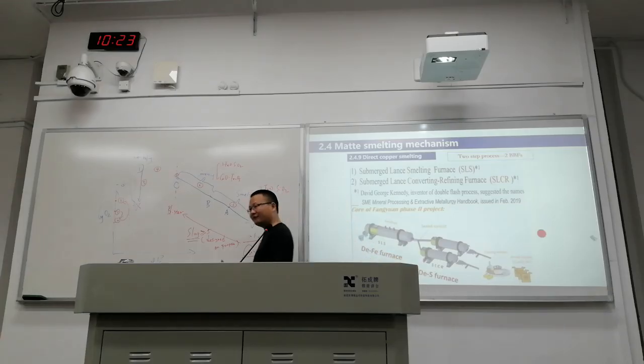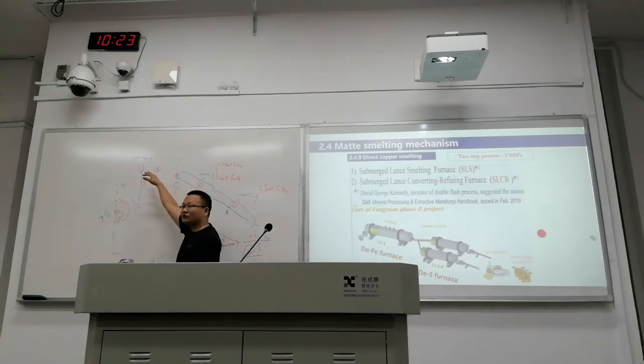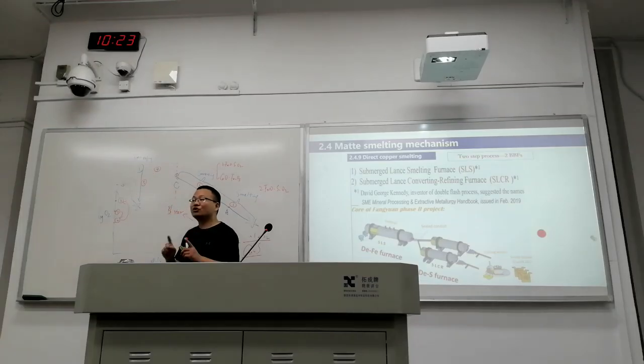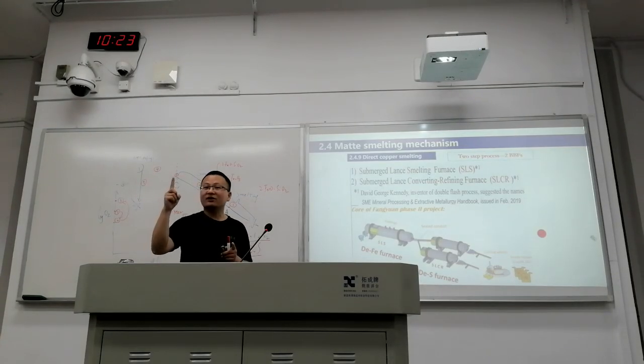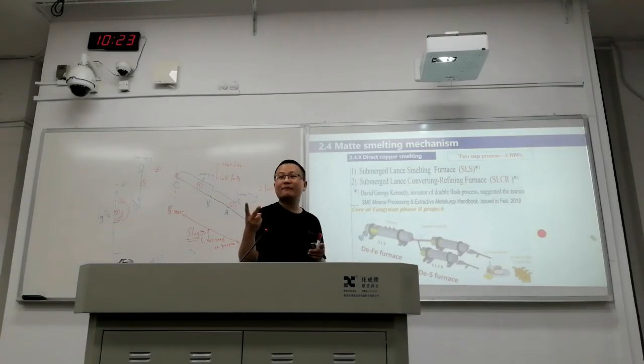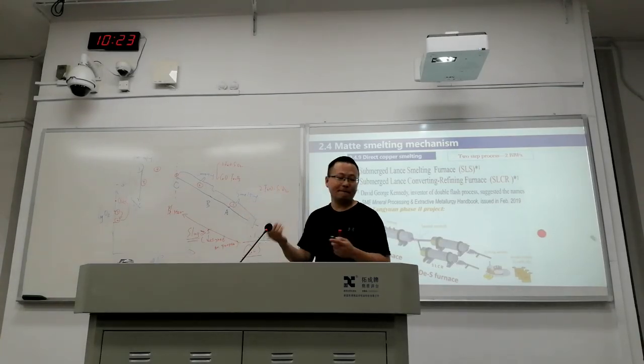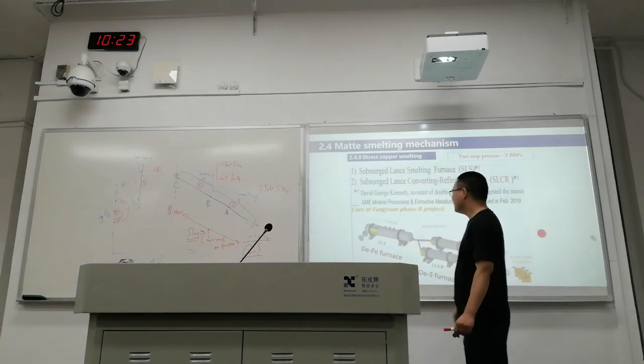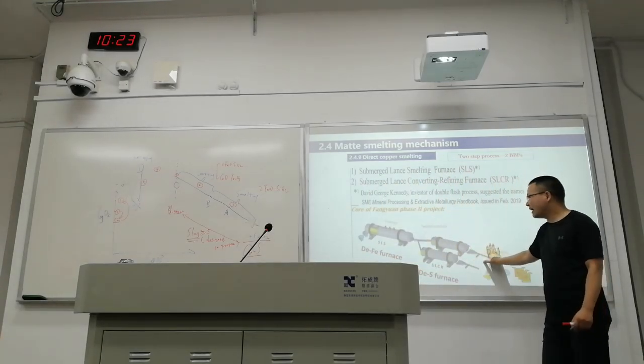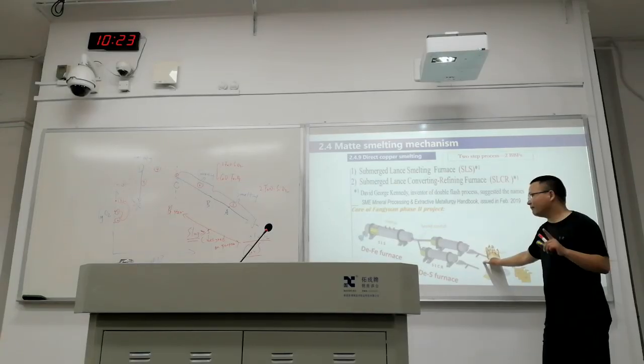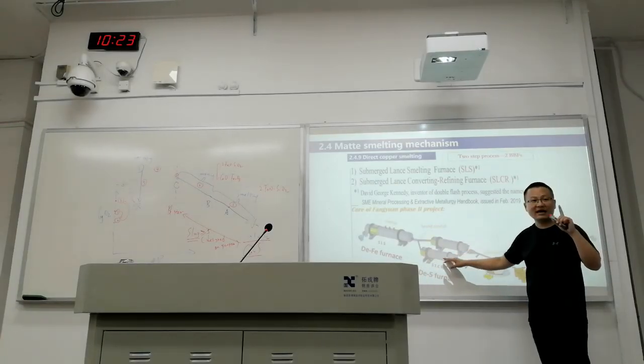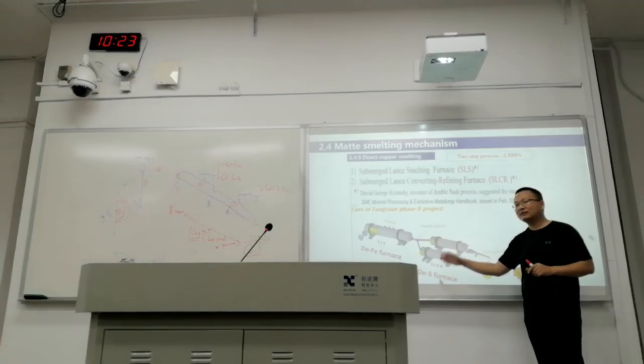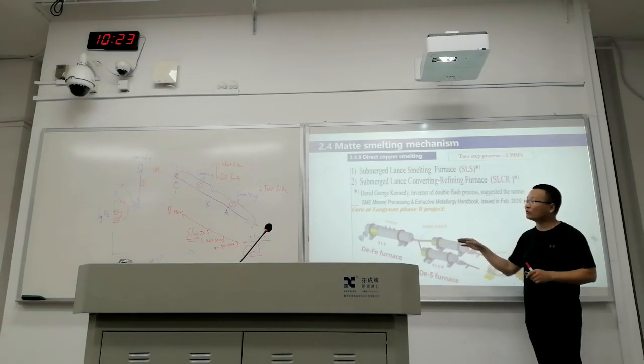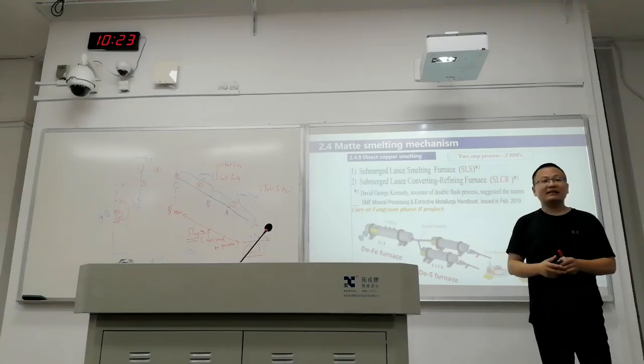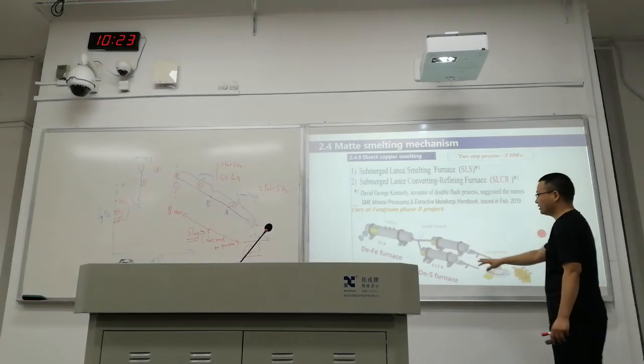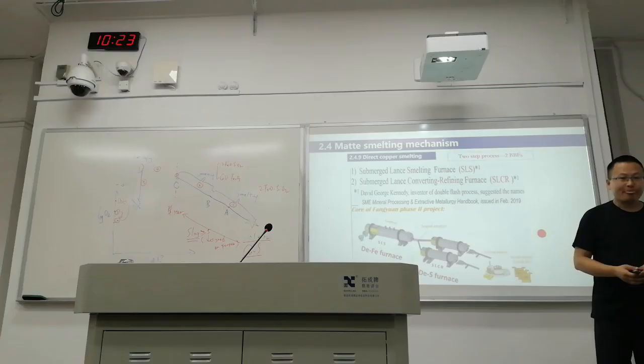So if they are oxidizing first, reducing secondary, so they have 2 phases in one furnace, or they should have 2 furnaces, right? Because the gas phase should be continuously controlled. So in this technology, they have chosen one furnace, but the furnace is running with 2 divided periods of time. One is for oxidation, another one, remaining time for reduction. So converting and actually reduction.